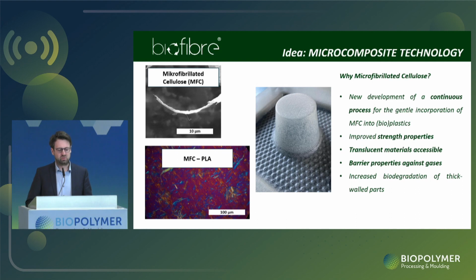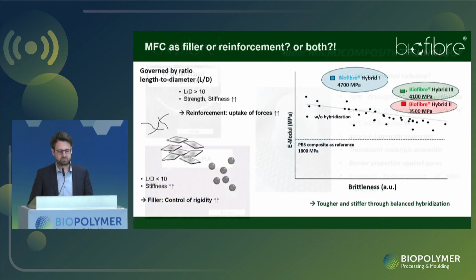And then we can have some nice aspects and benefits in terms of barrier properties. What is as well challenging for many bioplastics, as we heard before, is compostability. Most of the time certificates are restricted to some microns, like 50 to 100 microns film applications. But when we talk about injection molding parts, you talk about at least those 500 microns up to 1.5 millimeter for some packaging applications.